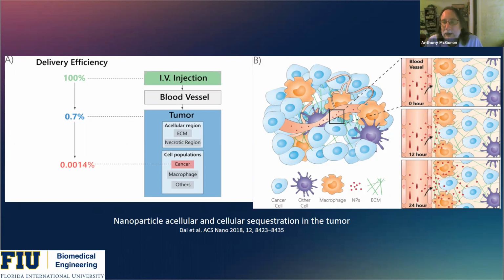When we talk about tumors, the tumor model that I was showing, these spheroids, they're avascular. They're about 300 microns in diameter, which is about the limit of size before they start generating a hypoxic core, because oxygen and nutrients can't get to the center of the spheroid. So treating larger and larger tumors becomes difficult because the interstitial pressure of these tumors builds up, and it inhibits the introduction of nanoparticles into the tumor itself. I'm not sure if that answered the question.